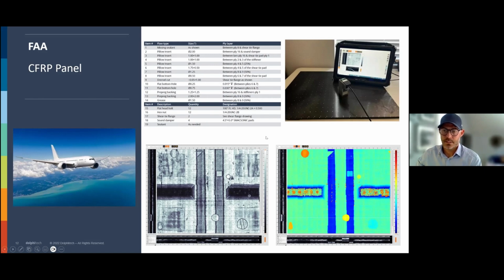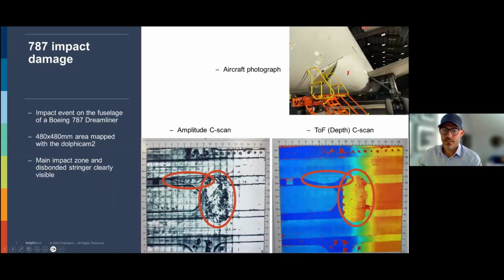So aerospace is maybe our biggest commercial market in addition to space. Here's another aerospace airline accident that happened. They drove this ladder into the fuselage, and they suspected it created a delamination. And as you can see from the impact damage down here, you have a huge delamination or impact damage here on the oval red one.